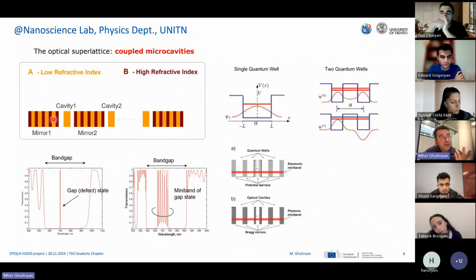While the mirrors are not metallic mirrors, it's not a single layer, it's the so-called Bragg mirror. So you have the Bragg condition. When you create a sequence of, let's say, two materials with two refractive indexes, N1 and N2, and you build their thicknesses in a way that N1 times D1, its optical thickness, is lambda/4, and the other one, N2 with its thickness D2, is again lambda/4. So they are all quarter wave, like quarter wave plates. When you put one after the other, you create a mirror.